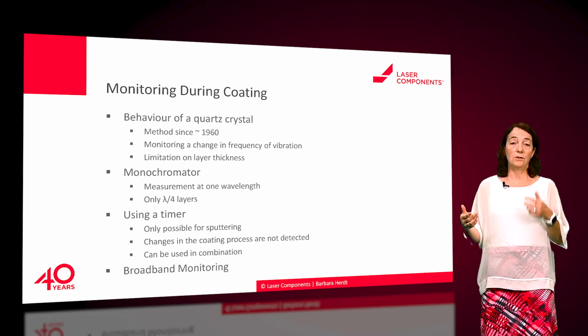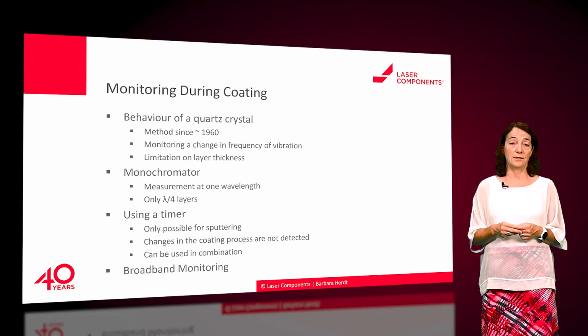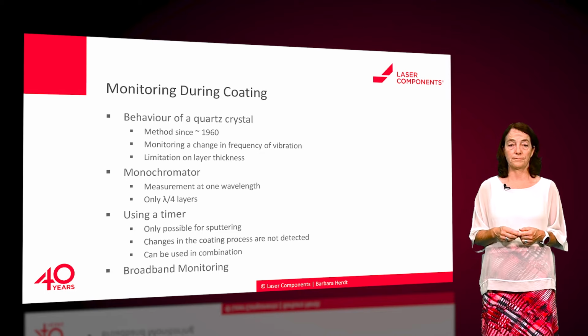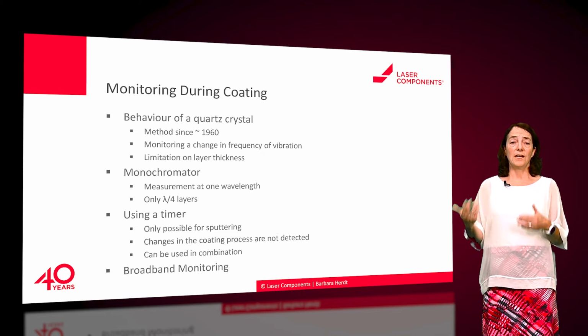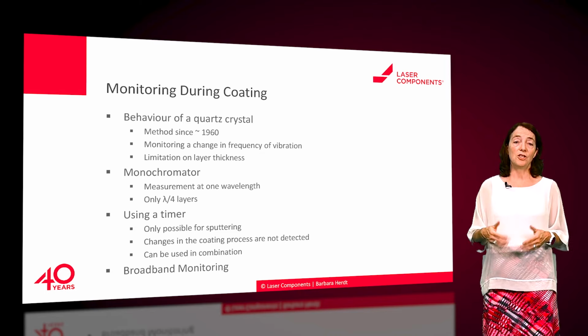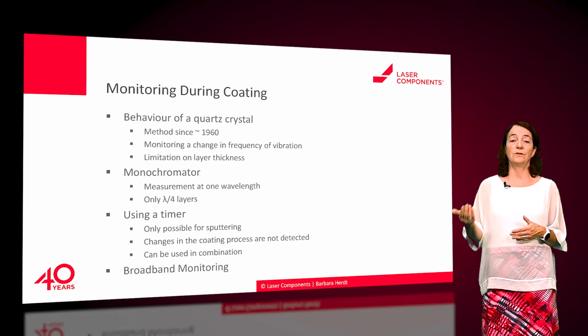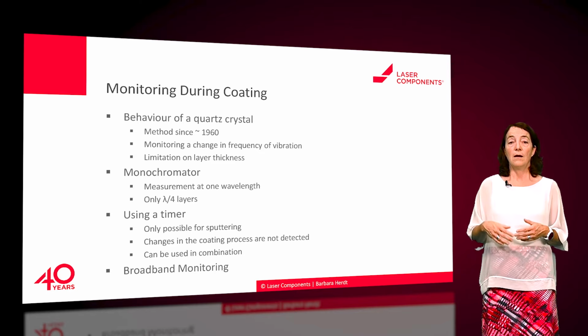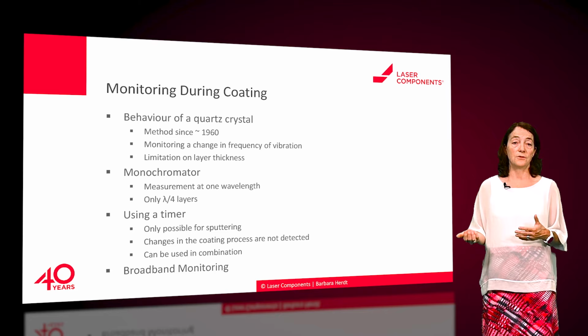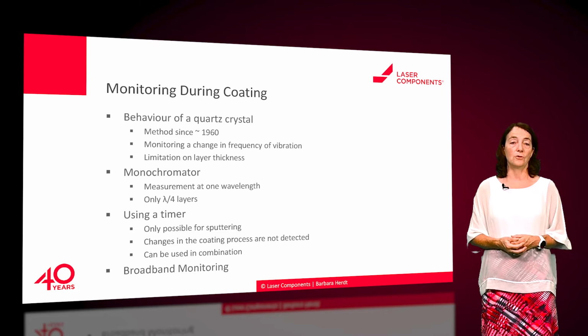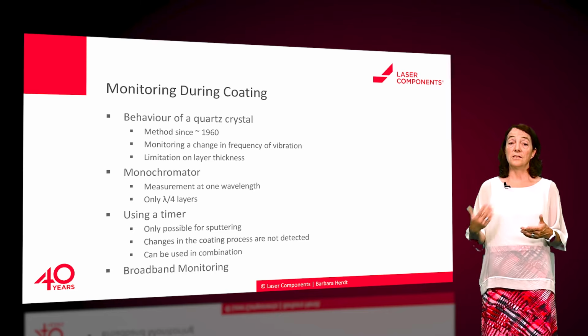There, the transmission on a test glass is measured at a single wavelength during the coating. By extrapolation of the coating design, the measurement gives you good information on the spectral behavior. But this is only accurate enough for designs with lambda/4 stacks, which often is sufficient for standard mirrors and anti-reflective coatings. A rather simple method would be using a timer.